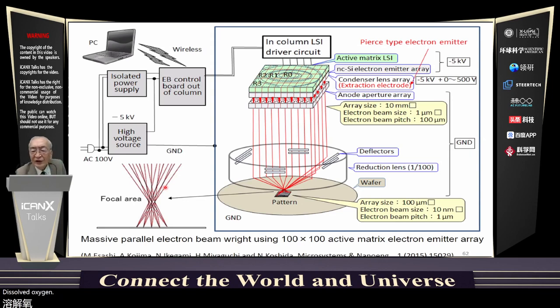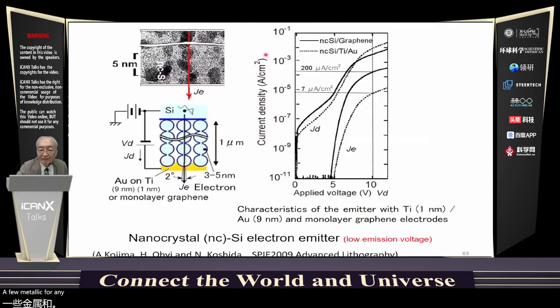Digital fabrication of LSI by maskless lithography is expected for cost-effective small volume production and efficient development of LSI. Massive parallel electron beam lithography systems, which have a 100 times 100 active matrix electron emitter array, have been developed. We used a nanocrystalline silicon electron emitter, which is made by electrochemical anodization of silicon in ethanolic hydrofluoric acid.